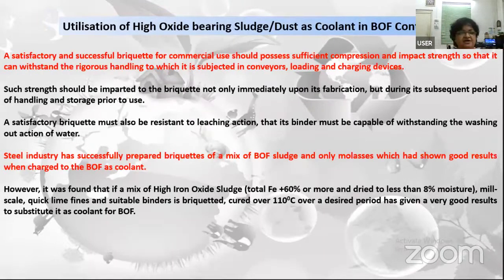So it is clear that a satisfactory and successful briquette for commercial use should possess sufficient compression strength and withstand the rigorous handling to which it is subjected on conveyors, loading and charging devices. The steel industry has successfully prepared briquettes of a mix of BOF sludge and only molasses, which showed good results when charged to the BOF as coolant. If a mix of high iron oxide sludge, that is total iron more than 60%, is dried to less than 8% moisture, and mill scale, quick lime fines and suitable binders are briquetted and cured above 110 degrees centigrade over a desired period, it will give good results as a substitute coolant for BOF.